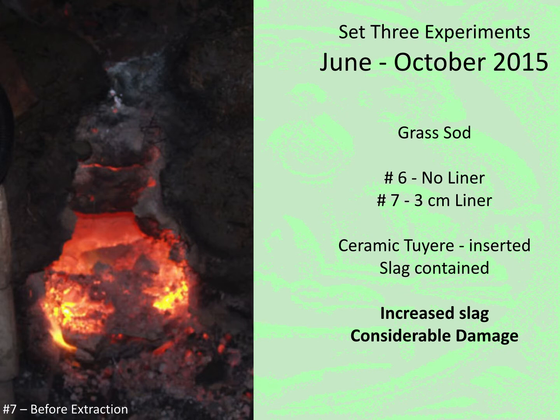Both of these furnaces experienced considerable increase in slag production. This in turn resulted in damage to the furnaces during the extraction process. In fact, in experiment number 6, it was impossible to get the bloom out while the furnace was hot.